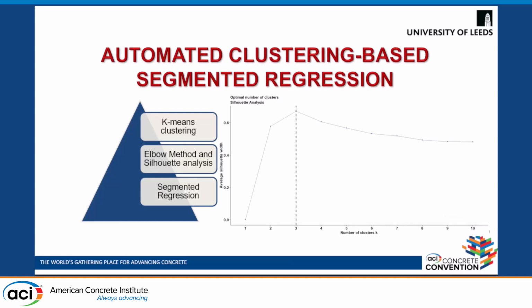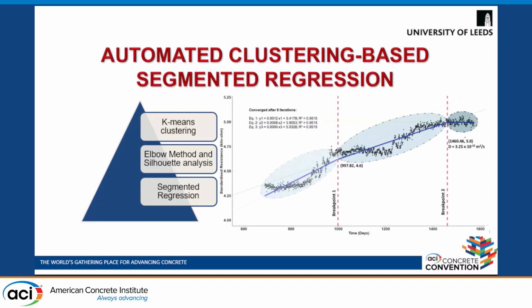To cross-validate it, we are using silhouette analysis, which identifies how well each data point fits into a certain cluster and identifies how many optimal clusters there are. In both cases, we have seen that there are 3 clusters. So the segmented regression is done on 3 clusters such that it divides the entire data set based on the change in the slope difference. And the final intersection point of the 2 clusters is considered as the time taken to stabilize resistance and the stabilized resistance value, while the 3 segments in each cluster show the rate of change in the resistance. And it can be seen from the 3 regression values that in the final regression, the values are almost stabilized.